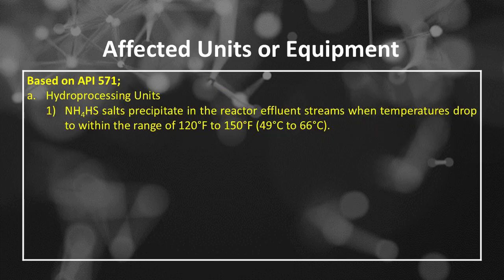Ammonium bisulfide corrosion or alkaline sour water affected units or equipment based on API 571, Number A, hydroprocessing units. Number 1. NH4HS salts precipitate in the reactor effluent streams when temperatures drop to within the range of 120 degrees Fahrenheit to 150 degrees Fahrenheit, or 49 degrees Celsius to 66 degrees Celsius.